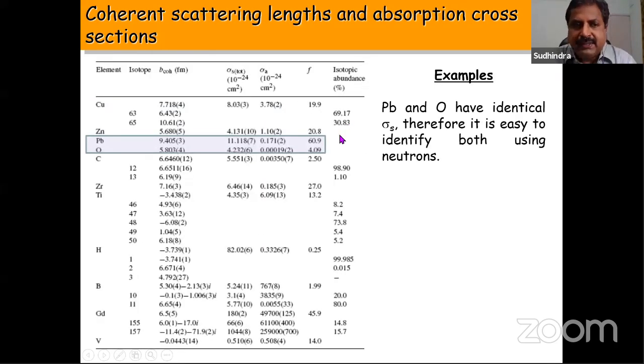Another example which I can give you is about lead and oxygen. In this case also, you can see that the neutron scattering lengths for lead and oxygen are of the same order. Of course, lead is more scattering than oxygen, but oxygen also scatters. But if you compare with that of the X-ray form factor, you can see that lead dominates the scattering compared to oxygen. When you do the analysis with X-rays, it is very unlikely that you will identify oxygen in the presence of lead. But in case of neutrons, you will be able to easily identify them. So these are the advantages of using neutrons over X-rays.